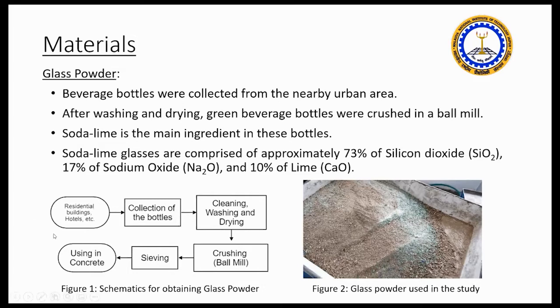This is the process of how we used the mechanism: collection, cleaning, washing, and drying, then crushing them, then sieving as per our size requirement according to IS 383, and then finally using it in concrete. In figure 2, you can see how these glass bottles are mixed into the natural river sand.